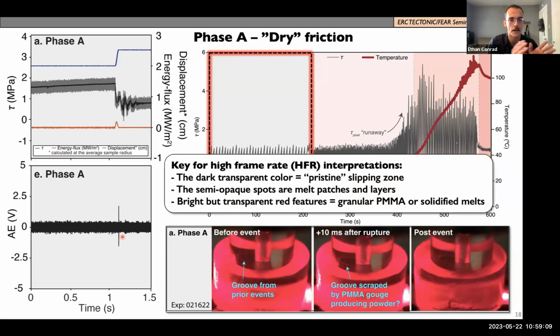And we're going to look at these quite a bit as we move through the talk. So the key for these interpretations is the dark transparent color that we see pretty much everywhere here is pristine slipping zone. It's basically the air in between the interface. The light can pass through very easily. And then the semi-opaque spots, which we don't see here, but we'll see moving forward, are melt patches and layers because the PMMA has broken down and reformed, and it starts to scatter the light as it passes through because the atomic structure is effectively changed. And the bright and transparent features, which we do see here, are granular PMMA or in later cases solidified melts.